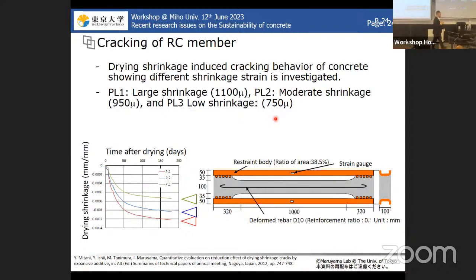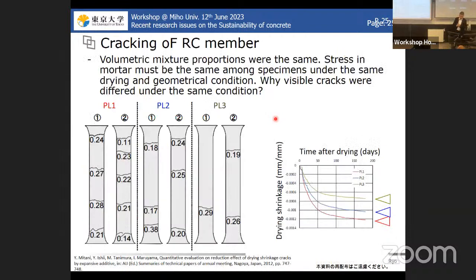So we compared these three concretes under the restraint condition like this. And these are the experimental results. So this is quite obvious. If we use the very shrinking concrete, we see a large number of shrinkage cracks.